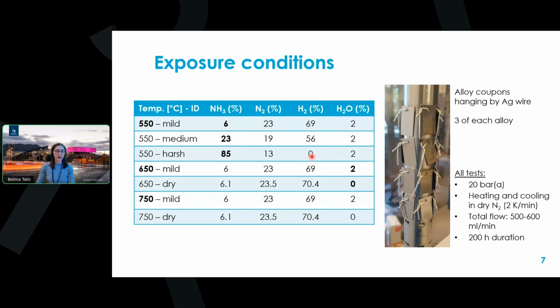And finally, we evaluated the impact of steam. Most of the tests were done with 2% of steam in the atmosphere, but we also did tests at 650 and 750 without any steam present. All of these 7 exposures were done at 20 bars of total pressure for 200 hours of duration. And we did heating and cooling in dry nitrogen atmosphere.